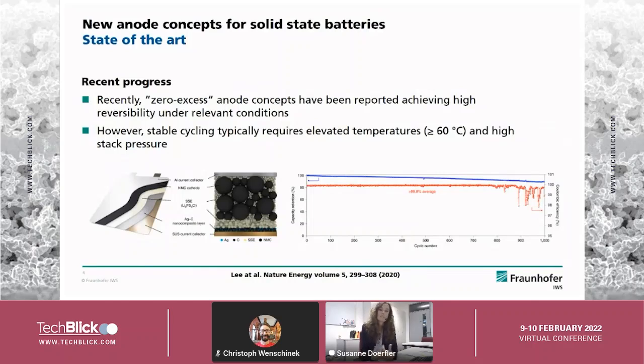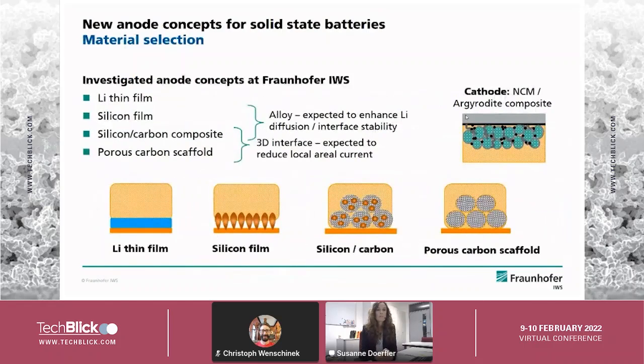However, this system can only be cycled at elevated temperatures, and high stack pressure is needed, which is of course detrimental when we think about OEMs that want to implement those batteries into cars, since you always need to apply the stack pressure. However, it's a quite promising so-called zero excess anode concept. The lithium comes solely from the NMC and is plated into this framework. At Fraunhofer IWS, we have been working on different anode systems for many years, especially first